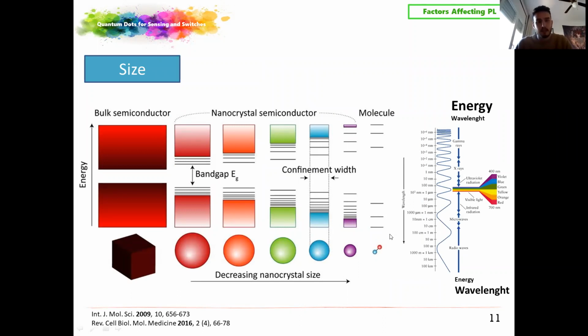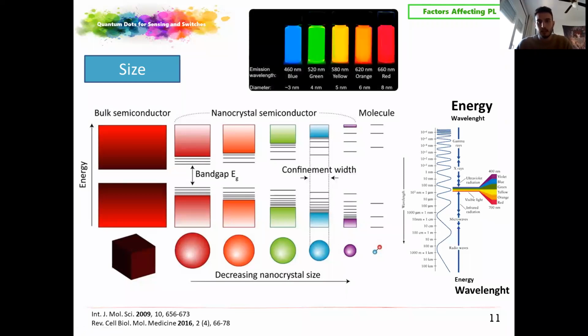This will affect the fluorescence wavelength, the range of the emission of this kind of fluorescence, because at smaller band gap energy, we will approach the red spectrum. However, when the band gap is increasing, the energy is higher, and we will get a shift near to the blue or violet spectrum. This is a very good property because based on the diameter of the nanoparticle, we can control the emission wavelength in different quantum dots.